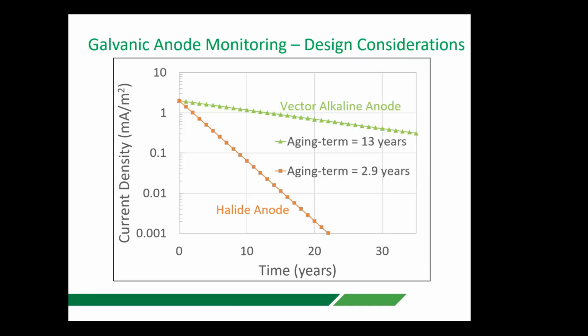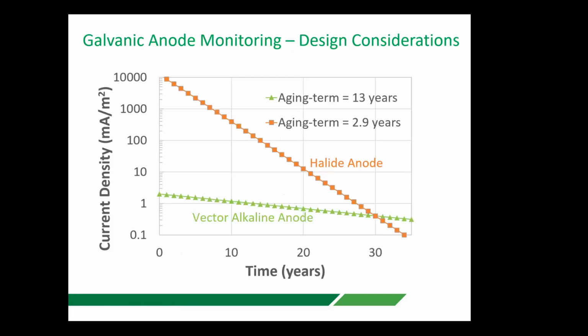And just to highlight how that aging factor can now be used, it gives us a lot more confidence of predicting where we want to be. So if, for example, we're looking for a current density of around, say, 0.4 milliamps per meter squared after 30 years, we know just by using the aging factor that we need to start at around 2 milliamps per meter squared. Now, if you use the alternative halide anodes and start at 2 milliamps per meter squared, you'll see that the current output would diminish so quickly that you're hardly producing any current even after 15 years.